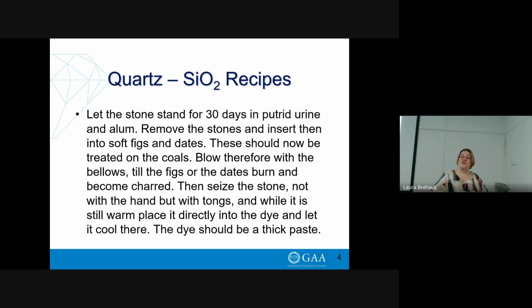So again, it's introducing thermal shock. The stone is cracking because it's cooled down very, very quickly. And the cracks reach the surface of the stone, which is really, really important. Surface-reaching fractures mean that the dye can then enter into those surface-reaching fractures. So these recipes sound a little bit ludicrous because we don't use stale urine or putrid urine. They didn't quite understand the scientific processes to be able to explain thermal quenching, but the process that they were doing was quenching the stone and dyeing it.